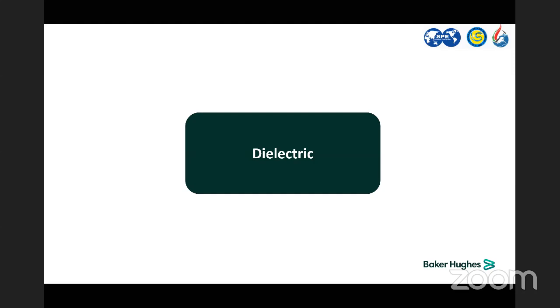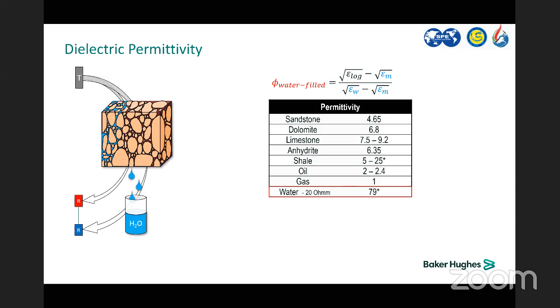We have an electromagnetic field, and we are measuring the phase and the attenuation. But the difference between dielectric and conventional resistivity is the frequency. In general, at low frequency, conductivity will be dominant. At high frequency, up to gigahertz, the dielectric will be dominant. And once we have the high frequency, we are able to get the permittivity, which is the main dielectric property.